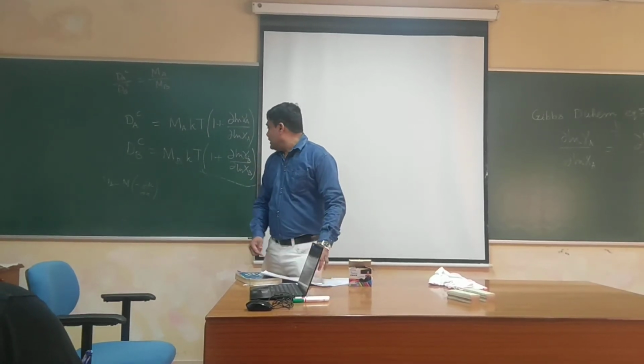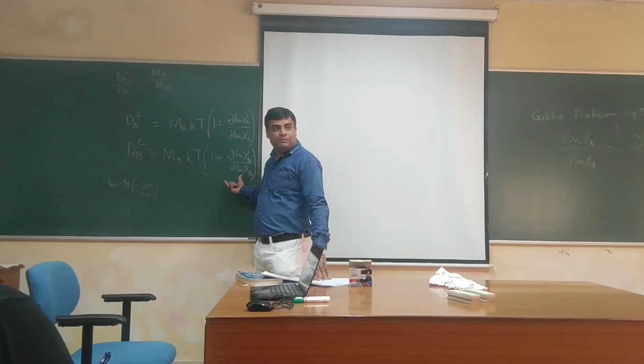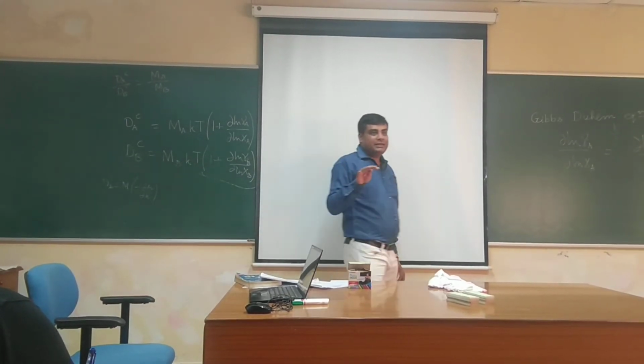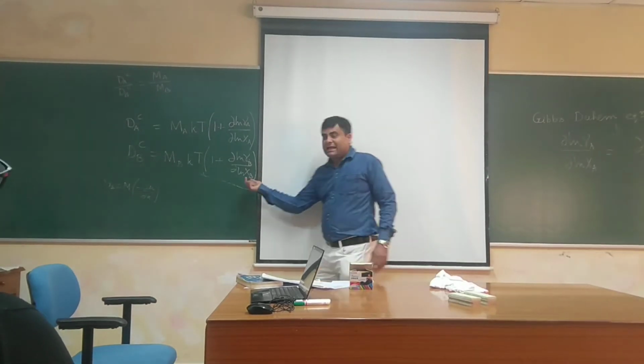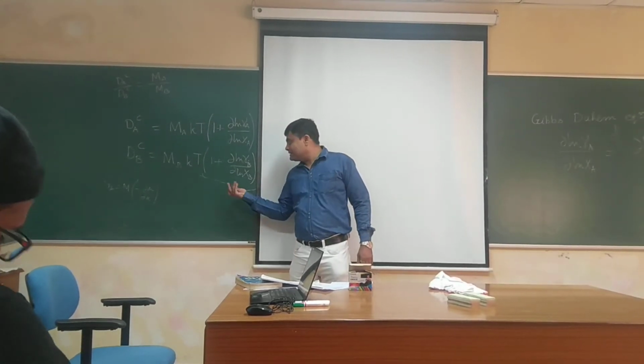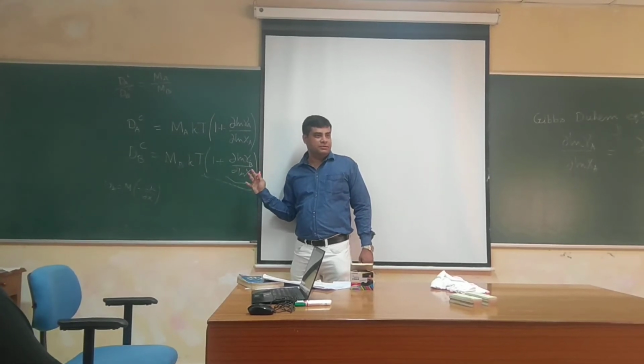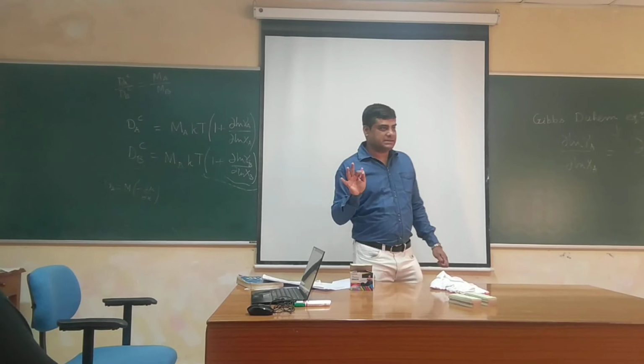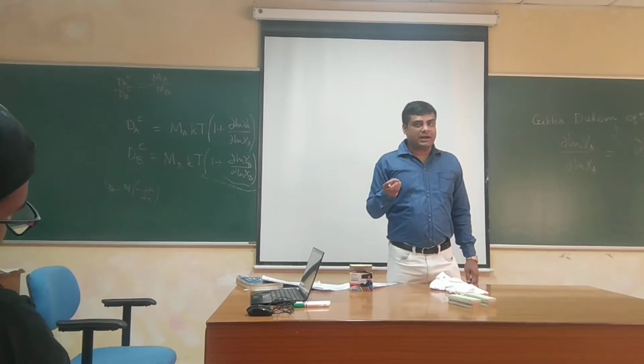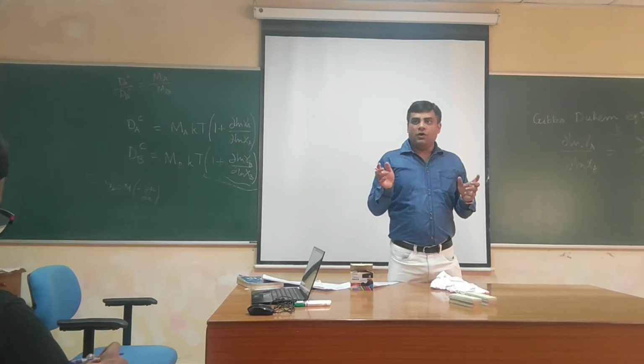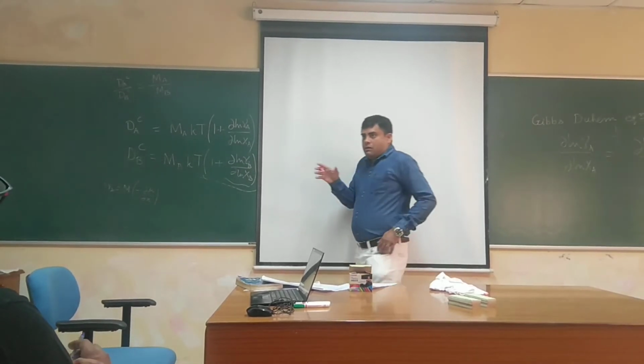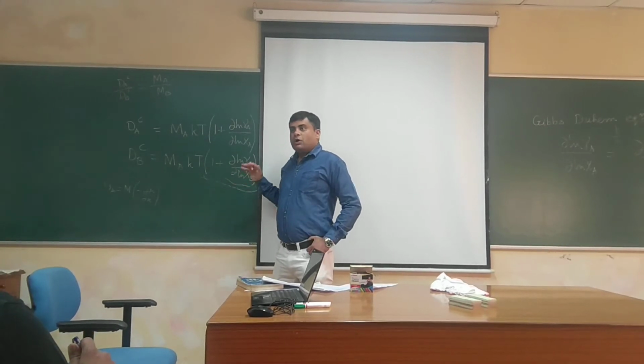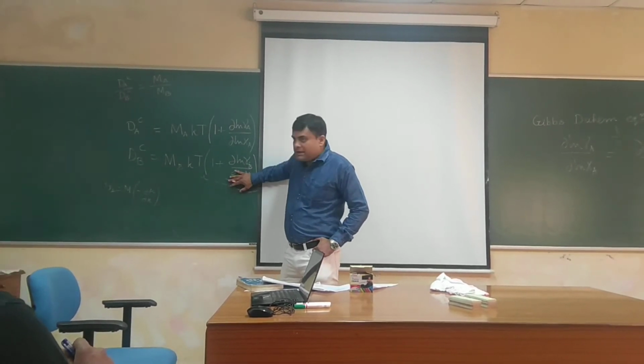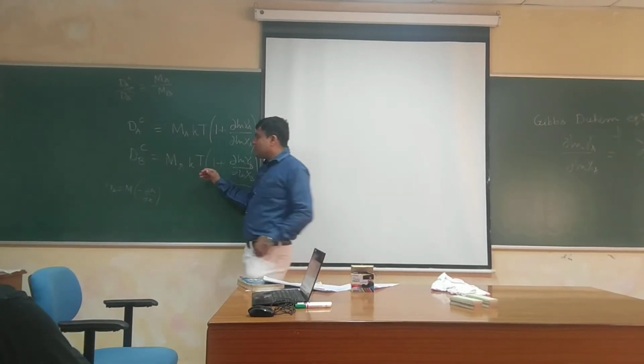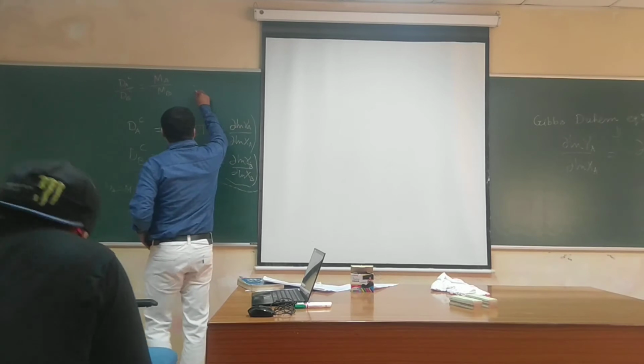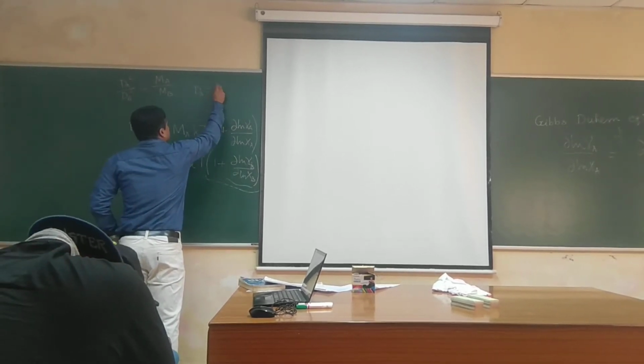there also this becomes zero, because in the homogeneous alloy there is no composition change, the xB is not changing, so this is not coming into picture at all. This becomes zero. For the tracer diffusion coefficient measurement using a small number of radioactive isotopes in a homogeneous alloy of a particular composition, composition variation is not coming into picture, so this becomes zero, this factor becomes 1. Actually for tracer diffusion coefficient DA should be MAkT